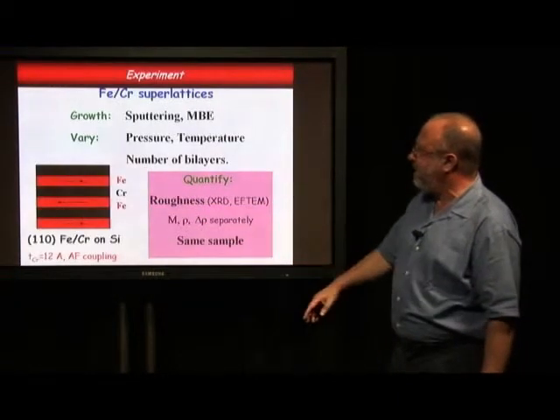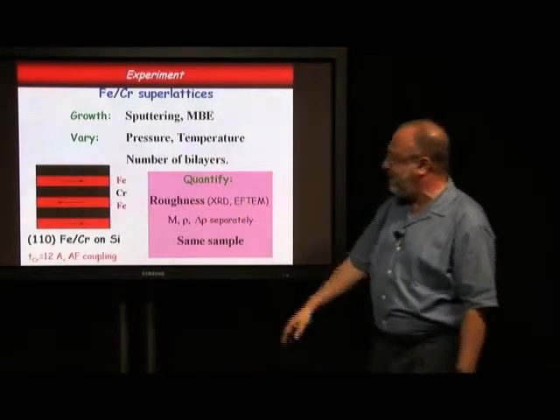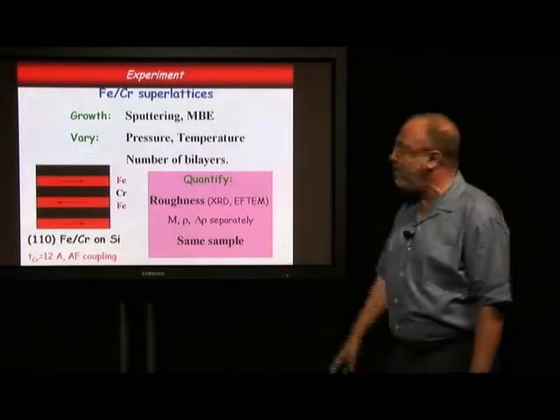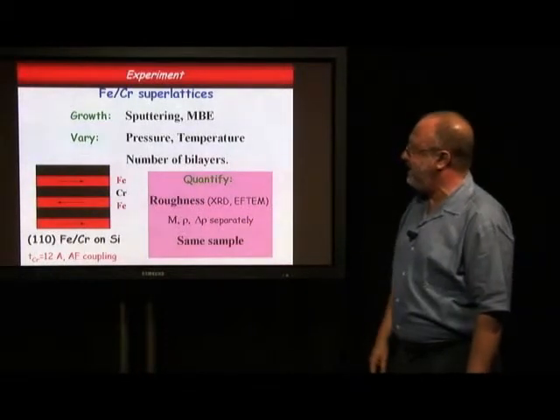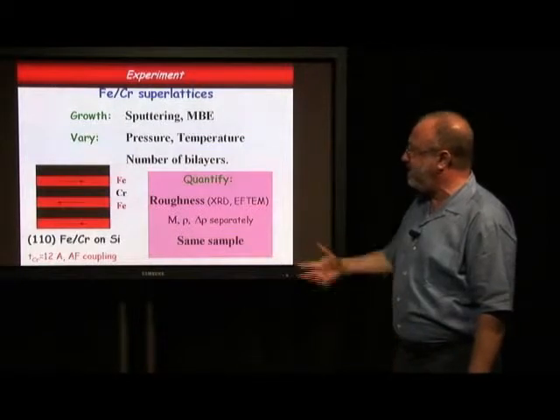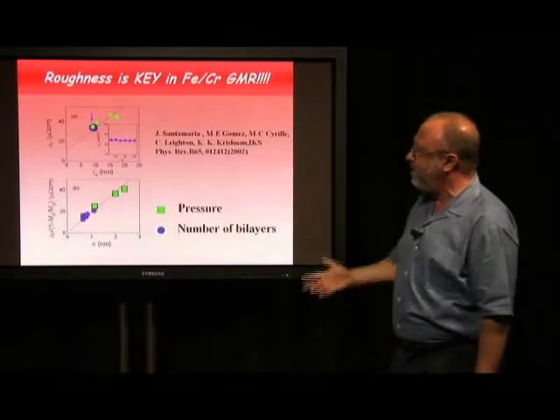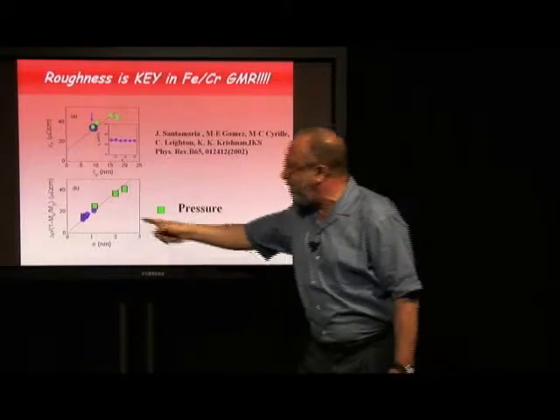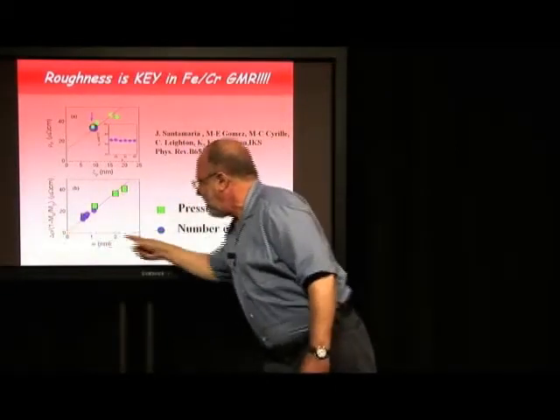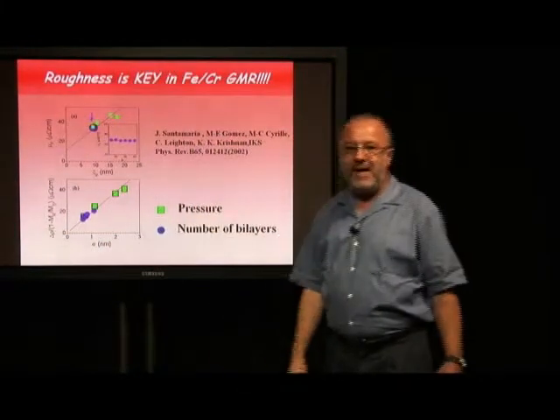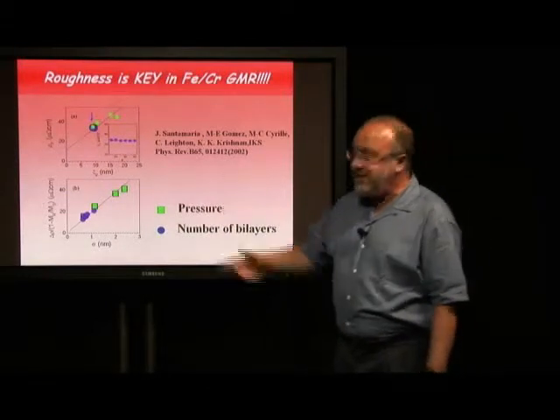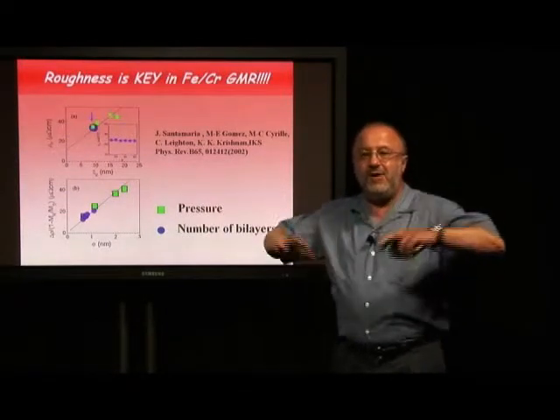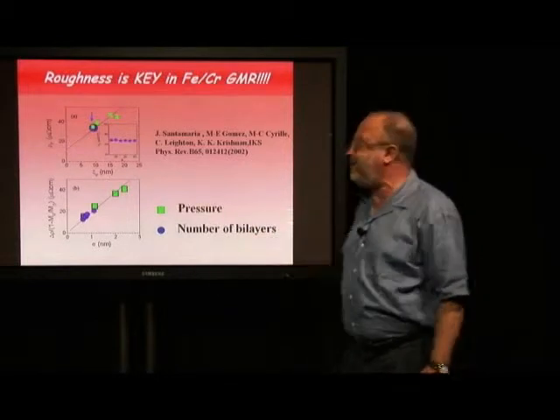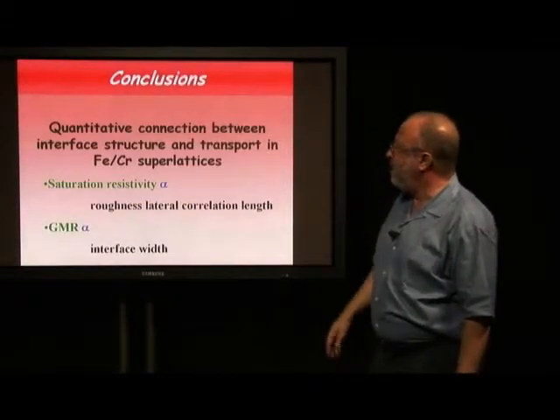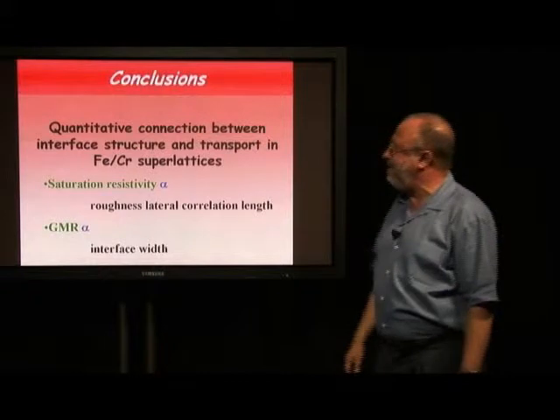Basically, what we did is an experiment in which we varied the roughness. We prepared these materials in a variety of different ways, and we studied how the magnetoresistance changes with all these properties. What we found, and here is the key, is this plot of the magnetoresistance as a function of roughness: the magnetoresistance scales with the roughness. What this tells you is that there are a lot of interactions at the interface, and most of the effect comes from the interfaces. The conclusions are, of course, in the papers, so I won't tell you more about that.